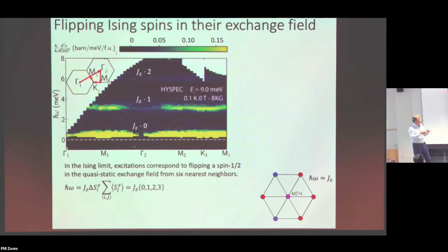But then, because it is a quantum fluctuating spin system, I should also expect that there will be some spins which are surrounded by a preponderance of red sites and fewer blue sites. That actually will cost an energy to flip that spin. You have to worry about delta S being 1 because it is a spin half degree of freedom, and so on. Then you'll find that this gives me an excitation exactly at Jz. That's what we should expect.